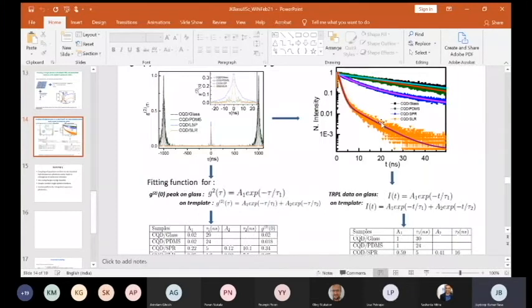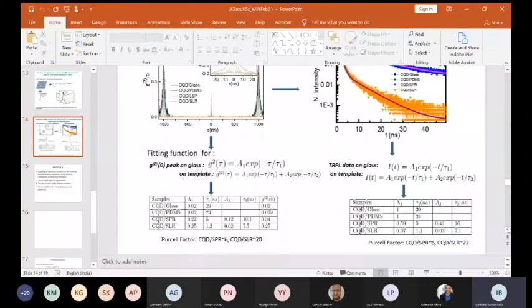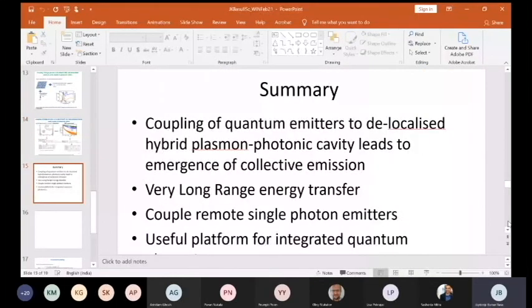Again, this is very long range. We are not talking about micrometers, or hundreds of micrometers, or millimeters, but long range. This emerges from the detailed analysis of the lifetime, because you don't see any signature in the spectral feature. But what is important is that we are talking about coupling between two isolated quantum dots mediated by the lattice mode. I think this has implications for various aspects of communication using single photons.